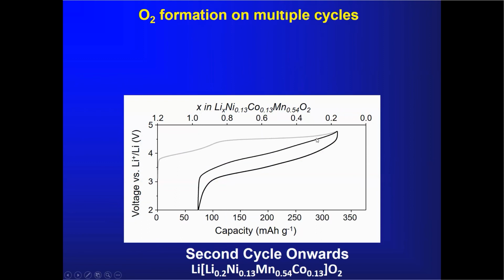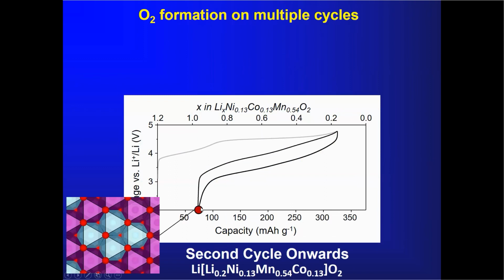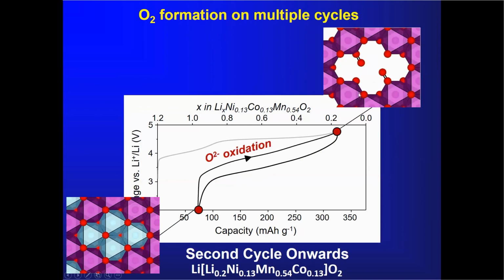And this is, in essence, what is driving that loss of voltage and loss of energy that we see in the load curve. Now, of course, I mentioned that after the first cycle, you can continue to cycle. And in this case, what happens is you oxidize the oxide ions again, you reform molecular oxygen, you come back down again, and the lithium ions go back into the same cluster. So this doesn't have an irreversible structural change. You still have some sort of breathing or distortions of the lattice, and that's probably responsible for the hysteresis, a slightly different pathway on charge and discharge, but much more structural similarity now, which is in keeping with the fact that we go around this hysteresis loop back to the same origin, in contrast to the first cycle.